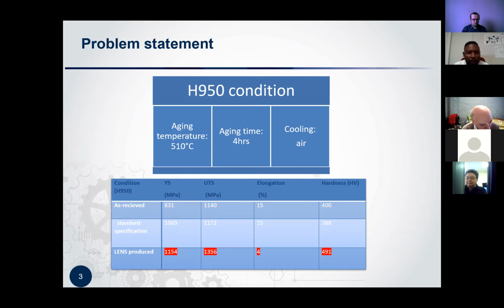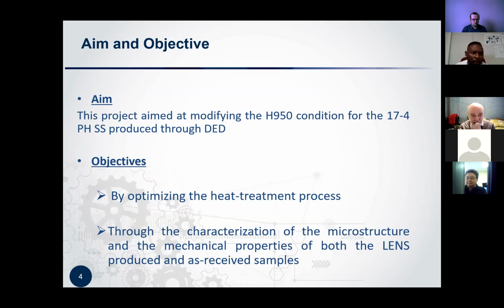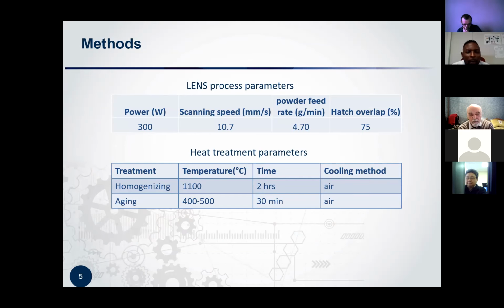So now we had to do a modification of H950 condition for the 17-4 PH produced through DED. This brings me to the aim: this study aimed at modifying the H950 condition for the 17-4 PH stainless steel produced through DED. This was achieved by firstly optimizing the heat treatment processes, which is the modification of H950 condition, and through the characterization of the microstructure and the mechanical properties of both the LENS produced and the as received samples or specimens.